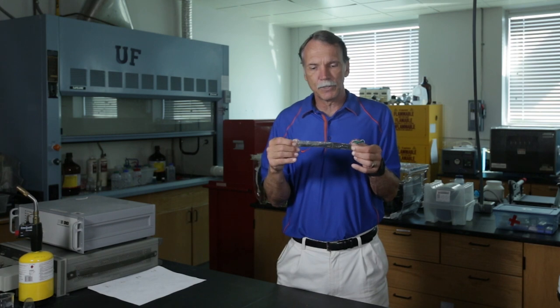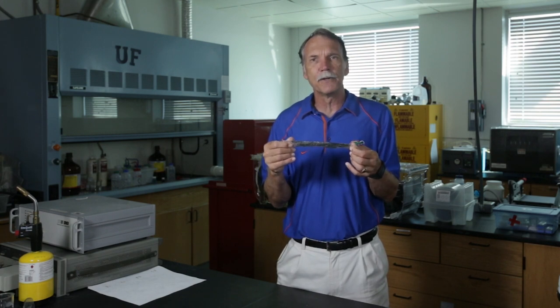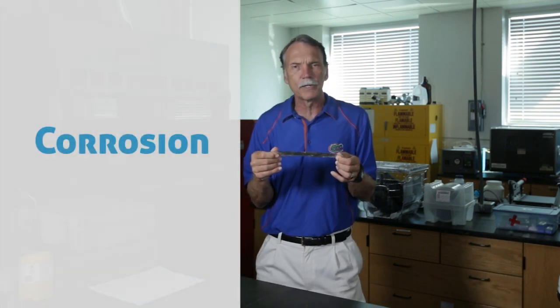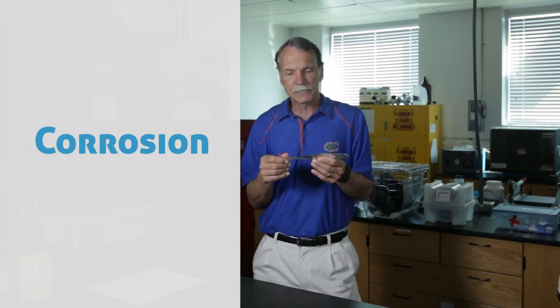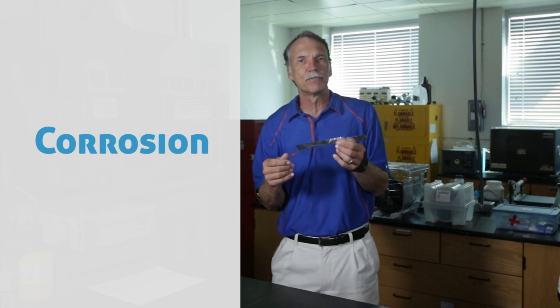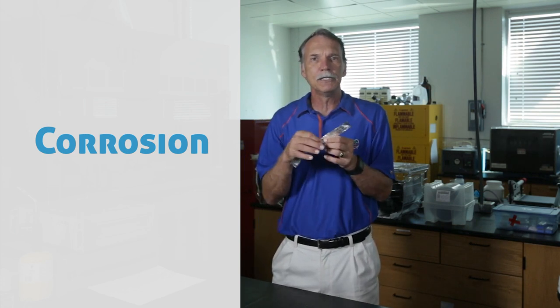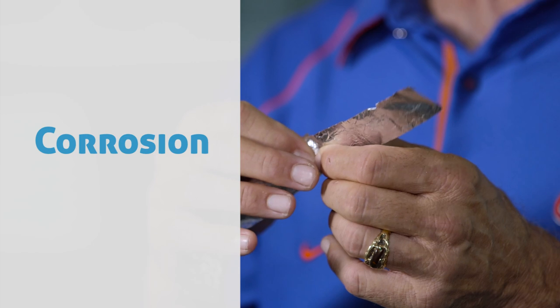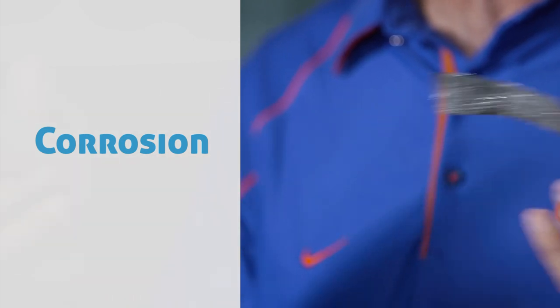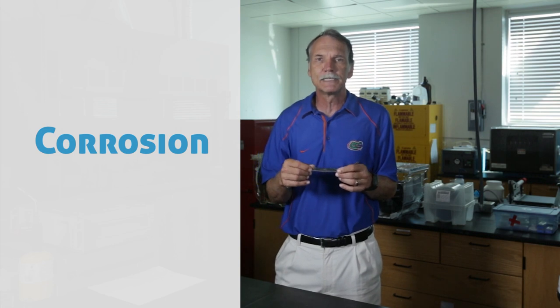So the next question is, well, does aluminum ever actually corrode? And the answer is yes. If you put it into a chlorine environment, say around salt water, then what happens is the chlorine will actually penetrate down some of the grain boundaries and it will form a little half-cell reaction in there, and you'll start to form pits at the grain boundaries, and that pitting is very common. And so if you look at your screen doors over at the beach, you'll often see pits in them from the aluminum corrosion.